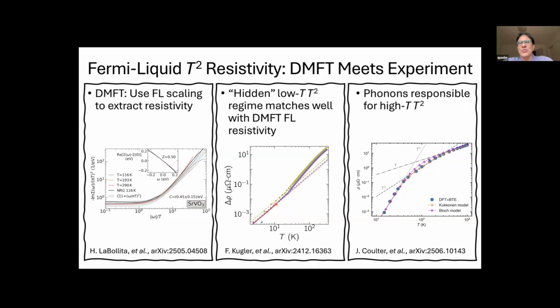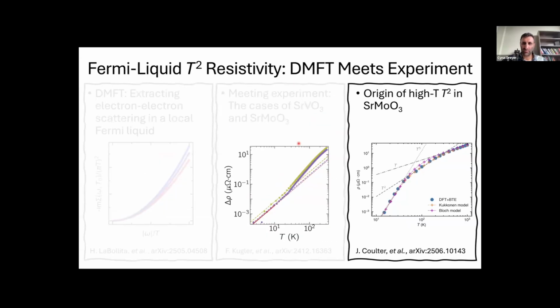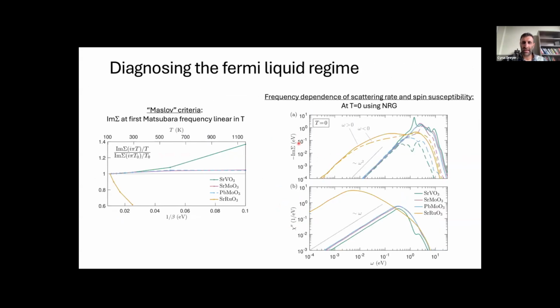But the follow-up question was, did you look at the spin susceptibility and see if it correlates at all with the T-square behavior? Yeah, so we did look at the spin susceptibility. I flashed through that very quickly with NRG. And for the Fermi-Liquid, we see basically a nice simple Fermi-Liquid regime in the frequency range that corresponds roughly to the Fermi-Liquid temperature that we see from other indicators like the Maslov criteria and the collapse of Im sigma and so on. Thank you.